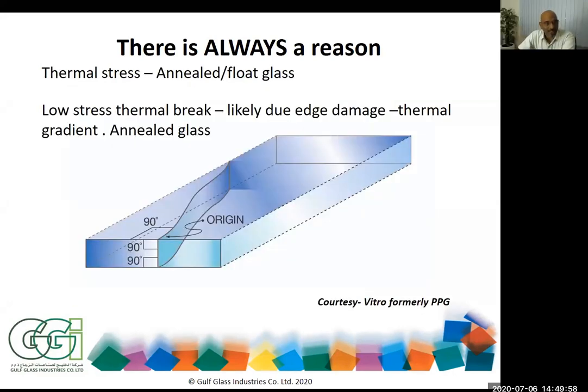There's always a reason, and thermal stress in annealed glass is one of the reasons. The pictures that you see are courtesy of Vitro, formerly PPG. They have a very good presentation on this, and I have taken some of it. The breakages that you see in annealed glass are one of the reasons designers are not using annealed glass, because they fear thermal stress breakage, likely due to edge damage and the thermal gradient that can happen in annealed glass. You can look at the glass and find out whether it is a low stress thermal break, because the origin will start from the edge of the glass and it will probably only have one crack along the glass. So this is how it looks.